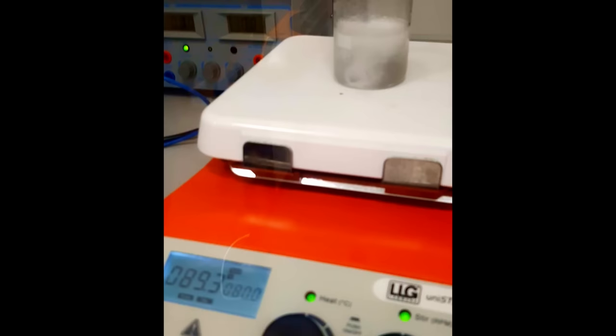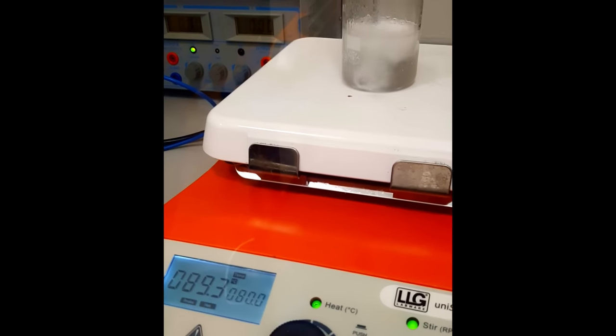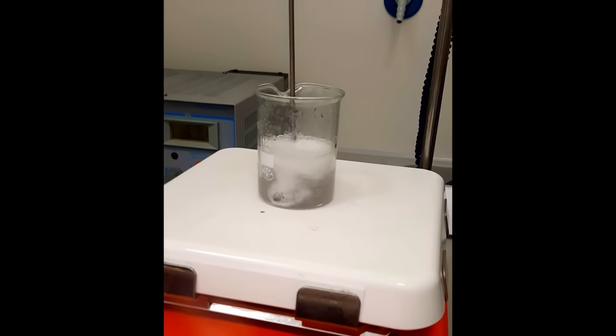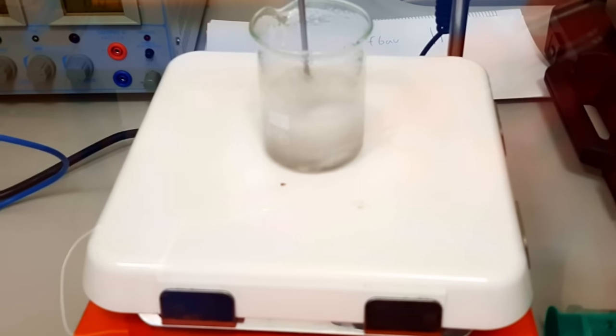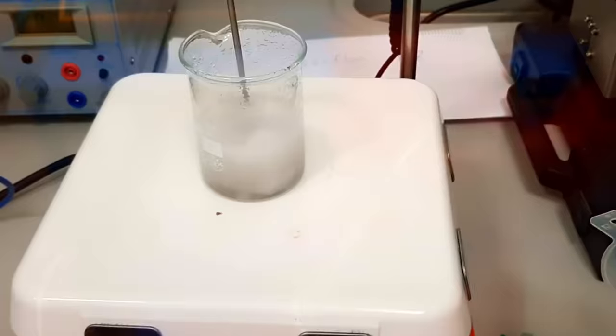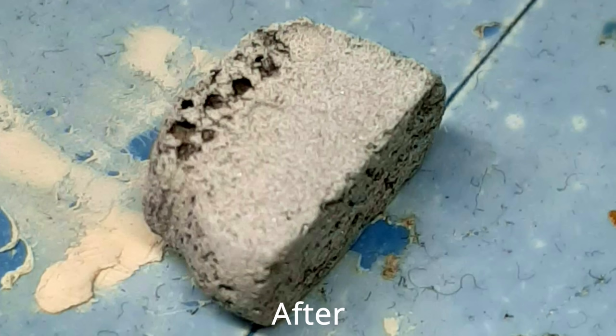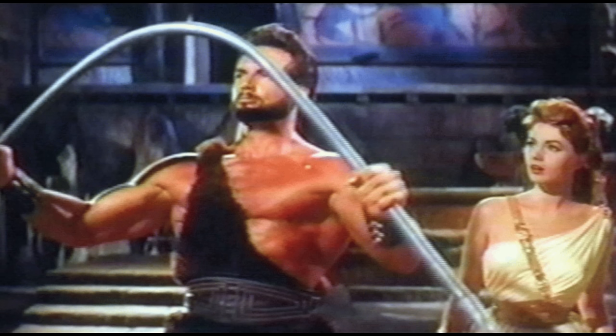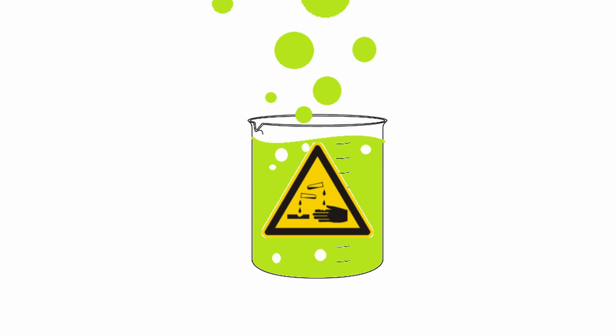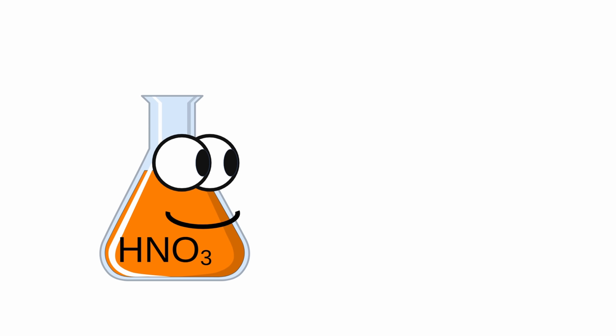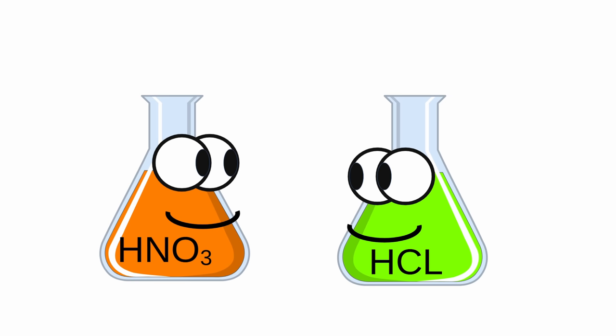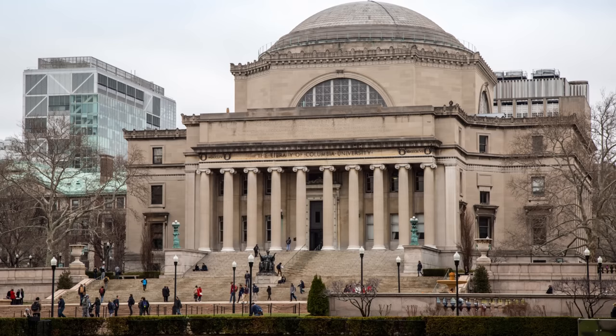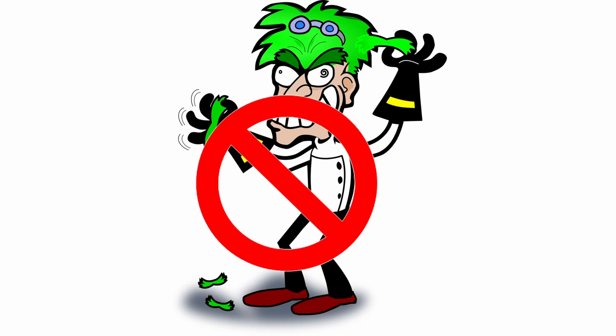Due to the parts being a hydraulic part, we can simply use acids in the channels to remove the support structures. If we are printing with aluminum we can use sodium hydroxide, which creates an exothermic reaction when it comes in contact with aluminum. This is a very fast and efficient way of removing material. If we want more strength out of our prints we have to use stainless steel. Dissolving that requires nitric acid and hydrochloric acid, both of which will put you on some sort of government list if you try to get it off the internet. Luckily, if you acquire these through a university, not only will you no longer be considered a danger to society, but you will actually receive a discount on buying them.